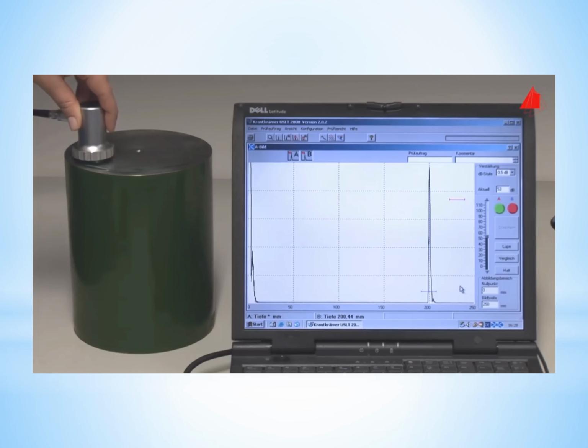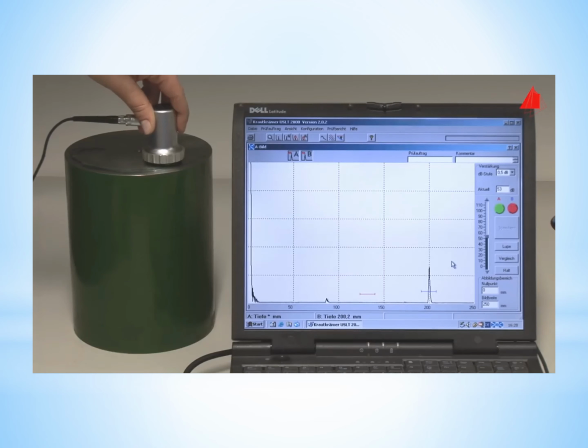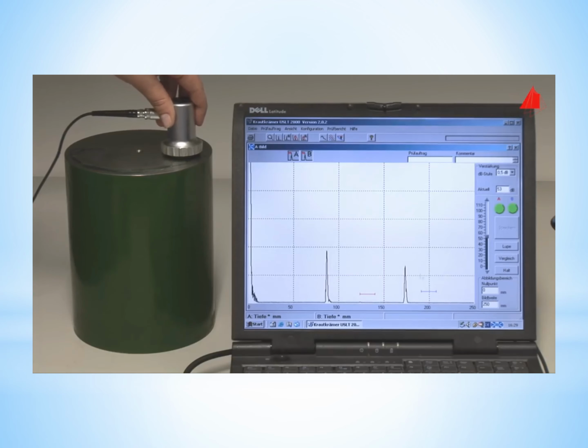The material tester scans the upper front end of the cylinder with a probe and observes the monitor. A defect echo appears on the monitor. This defect is located in a depth of 130 mm below the surface. Another echo indicates a defect in a depth of 87 mm. The second smaller echo at 174 mm is caused by double reflection on the same imperfection.